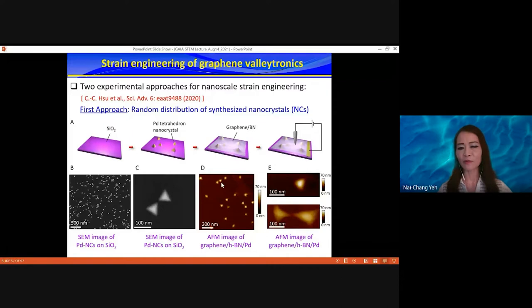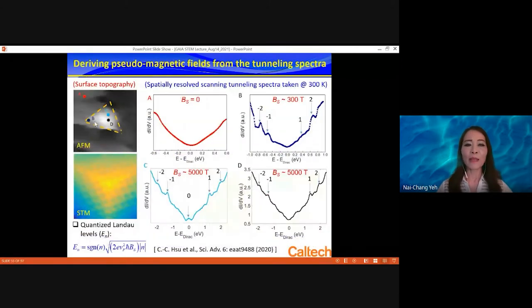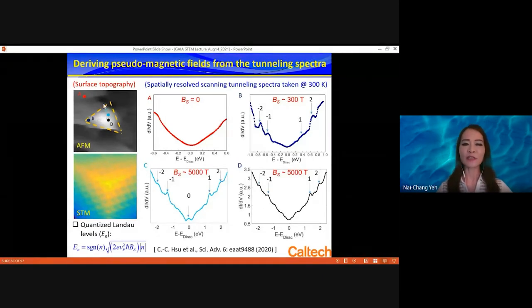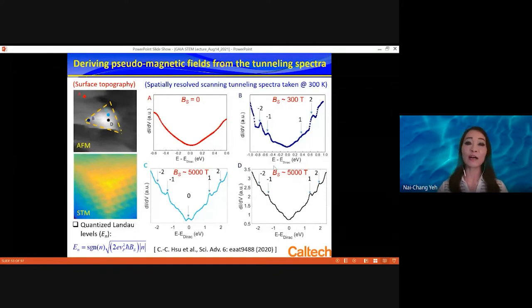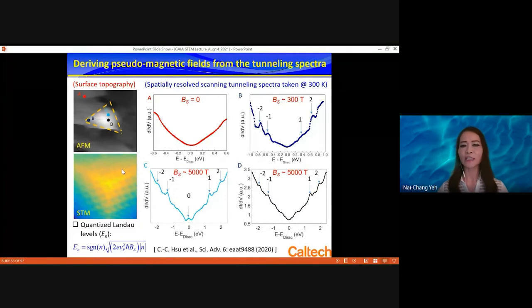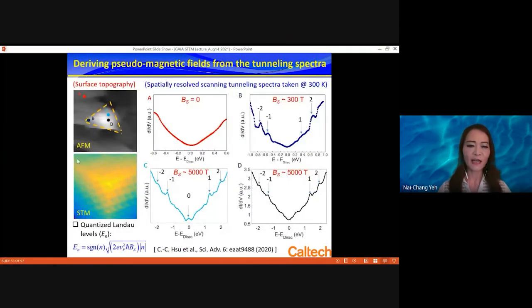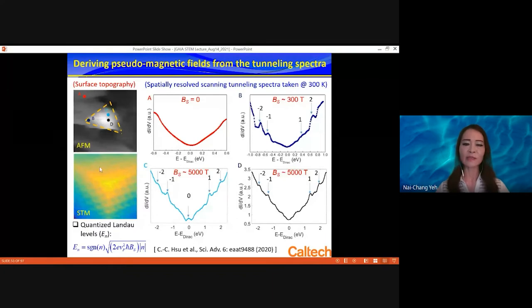With just nano crystals and graphene on top, zooming in you can see that if there are two crystals, there's a wrinkle in between. Doing STM studies with the tip far away, the tunneling conductance looks like the expected red curve with no strain. But as you bring the tip to strongly strained areas, you start seeing peaks that correspond to very high pseudo-magnetic fields — as high as thousands of Tesla. These are pseudo-magnetic fields because no real magnetic field is applied; the total magnetic flux is zero. STM topography images show real atoms and confirm the graphene is truly strained.